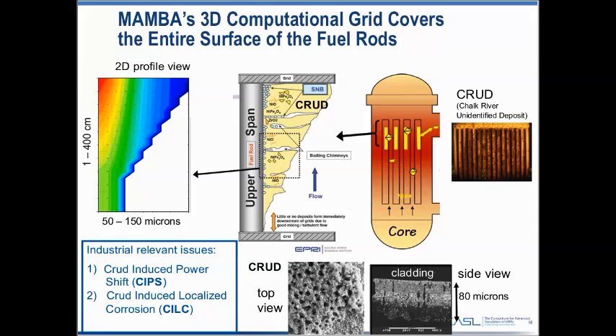Within this deposit you have boiling chimneys. The little round circles represent the vapor bubbles that are forming. It's typically a nickel ferrite material, a porous material with about 0.7 porosity. There are other species such as nickel oxide and zirc oxide in the CRUD layer.